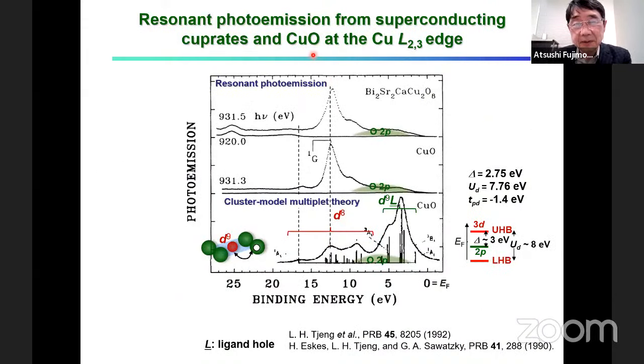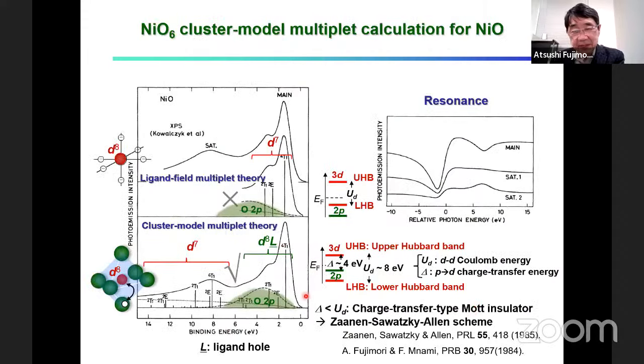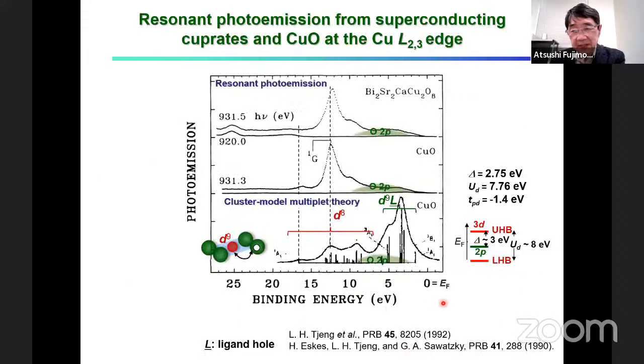Now, for cuprates, resonant photoemission has been done just after the discovery of high-Tc cuprates and the model compound copper oxide. Resonance occurs at a lower deep binding energy, so that the electronic structure is almost similar to this nickel oxide.